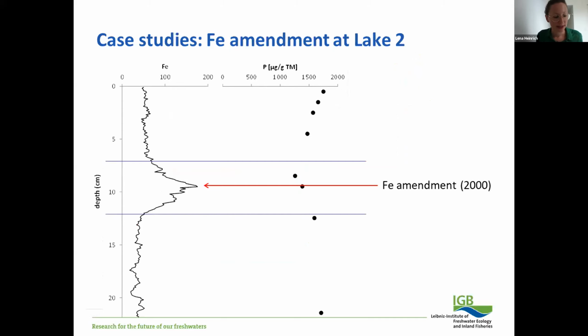However, iron amendments do not always work that well. After the iron amendment at Lake Plötzensee, also in Berlin, the iron content increased, but after a few years, the content was almost back to the background value. And after the removal of the phosphorus in the water column at the moment of the iron amendment, there was no indication that the iron in the sediment of this lake was or is a phosphorus sink. The iron-related phosphorus fractions account for less than 40% of the total phosphorus found in the sediment over the whole profile, and Vivianite or other stable iron-phosphorus minerals have not been identified.